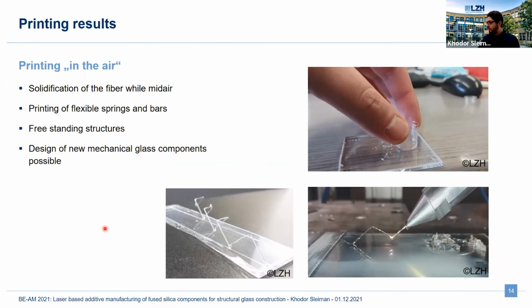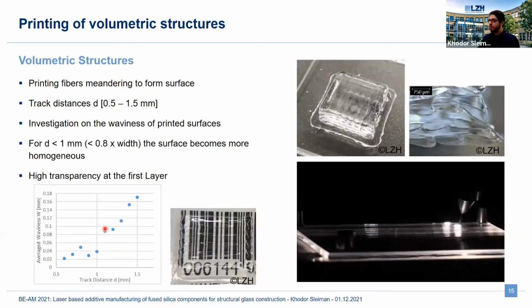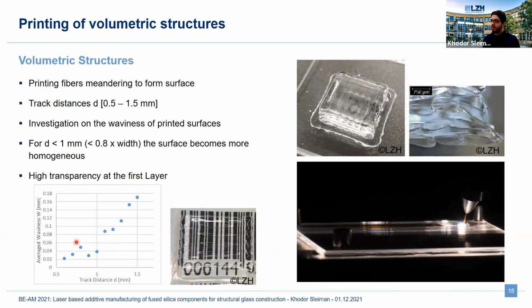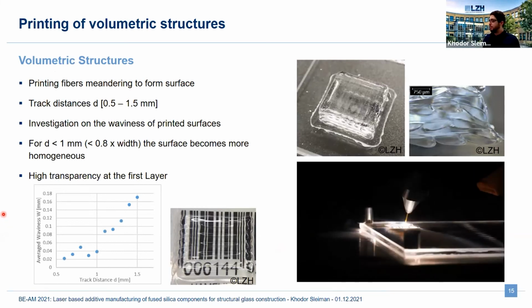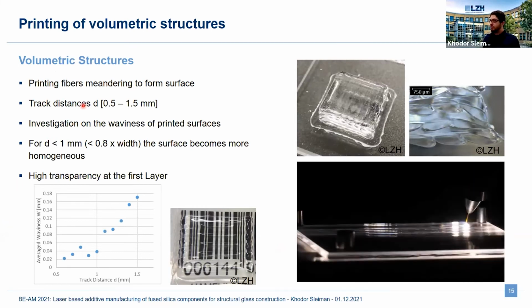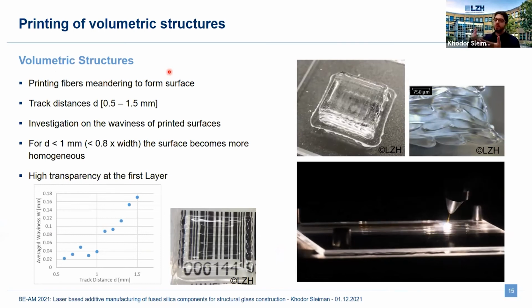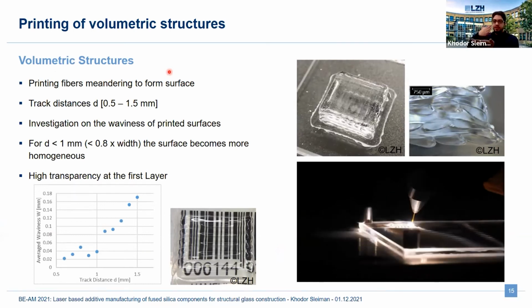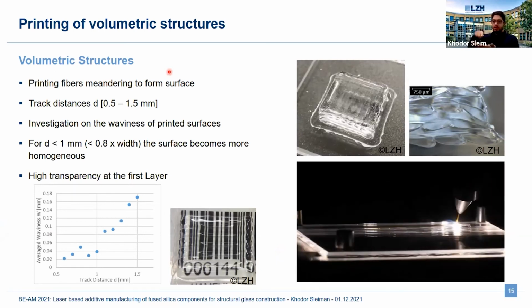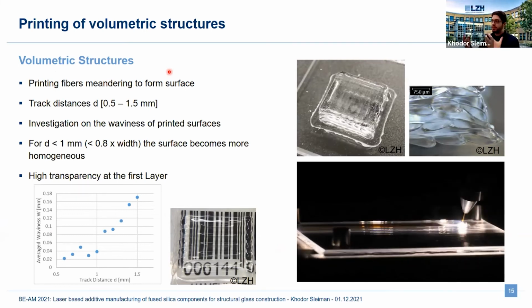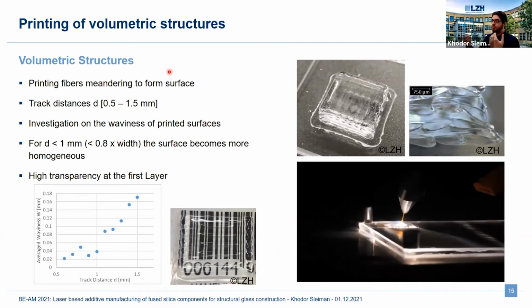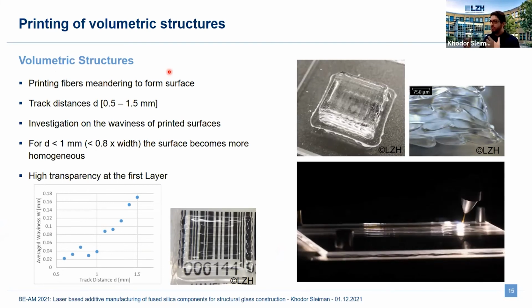So on the other end of the spectrum of 3D printing disciplines are the volumetric structures, which we also investigated in the form that we printed or deposited the fibers in a meandering manner next to each other with track distances between 0.5 and 1.5 millimeters.